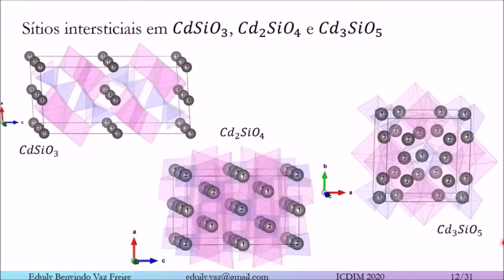So now we will identify where the interstitial ions can be inserted. For that, we found regions of our solid where there is at least 1.5 angstroms to the nearest ion. We found 3 symmetrically non-equivalent positions for the interstitial ions in the CdSiO3 matrix, and 2 symmetrically non-equivalent positions for the interstitial ions for the Cd2SiO4 matrix, and we found 3 symmetrically non-equivalent positions for the Cd3SiO5 matrix.